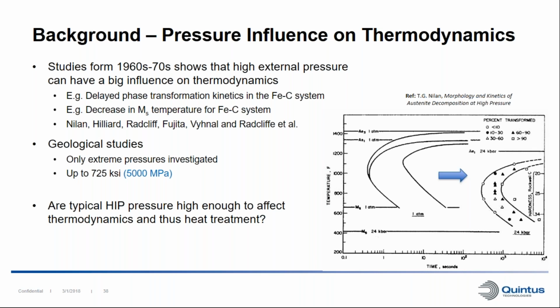Stuff that they've seen is delayed phase transformation kinetics in the iron-carbon system, decrease in martensite start temperature also for the iron-carbon system, etc. As we can see here on the lower right, we have a TTT diagram, and we can see that the position of the pearlite nose is very different when you perform it under atmospheric pressure or at 24,000 bar.